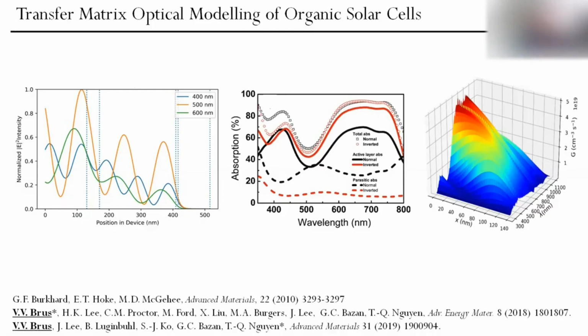And by doing that, we can calculate the absorption spectra in the active layer, and some parasitic absorption in contacts at electrodes. So we don't want to lose light at electrodes because we don't generate excitons. We generate excitons only in the active layer. So we want to design this device structure in such a way that we have maximum generation rate within the active layer. And eventually what we can get is some three-dimensional distribution, like a plot of generation rate as a function of wavelength and position in our active layer. So we can really, within this nanometer range, see where most of the charge carriers are generated. It's not charge carriers yet, most of the excitons are generated.